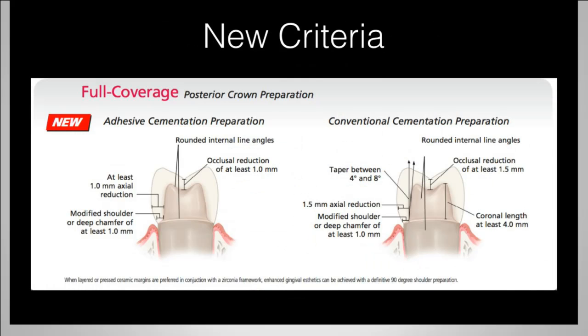Interestingly enough, Ivoclar this year released a new drawing. And in their new drawing, what they state is, essentially, if you're willing to bond your restorations, so if you're willing to use an adhesive cementation protocol where a bonding agent and a resin cement are used, you only have to reduce 1 millimeter occlusally. You only need to reduce 1 millimeter axially as well. On the other hand, if you want to use something like a self-adhesive resin cement, you do not want to use a bonding agent, you do not want to go through the full bonding protocol, you do need to take more tooth structure away. You need to remove about 1.5 millimeters occlusally and about 1.5 millimeters in the mid-axial and then 1 millimeter in the gingival third.